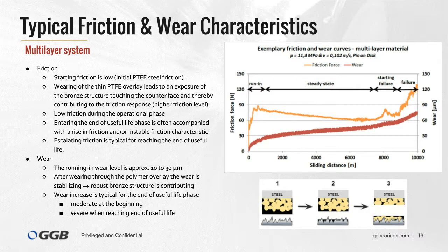We see a clear increase in friction, caused by a structural alteration at the interface of both contacting surfaces. During the first sliding meters, the PTFE-based overlay wears and is partly transferred onto the counter surface, resulting in exposure of the subjacent bronze structure. The bronze structure is now directly contributing to the sliding process, resulting in a PTFE lubricated bronze-steel contact, which now responds with higher friction.